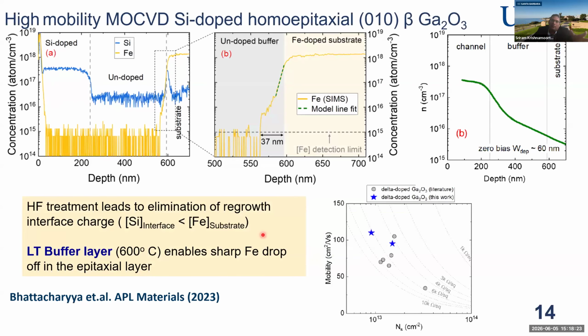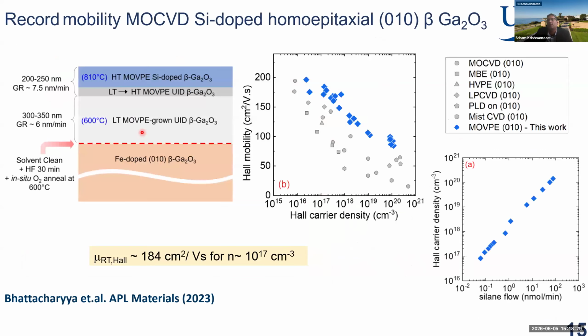It helps us do this kind of engineering of the stack to be able to get high mobilities. So putting these ideas together, by figuring out the surface preparation techniques, a low temperature initial layer and a high temperature channel layer, we've been able to get across-the-board enhancement in electron mobility in these films. And you can see the wide range of doping capability we have, 10 to the 16 to 10 to the 20, which nicely scales with the flow of silane. And so this helped us achieve some record results in terms of electron mobility in the channel layer.